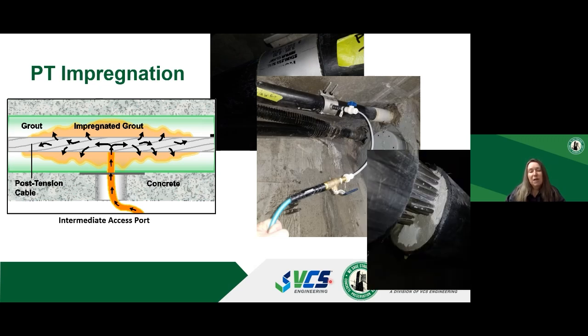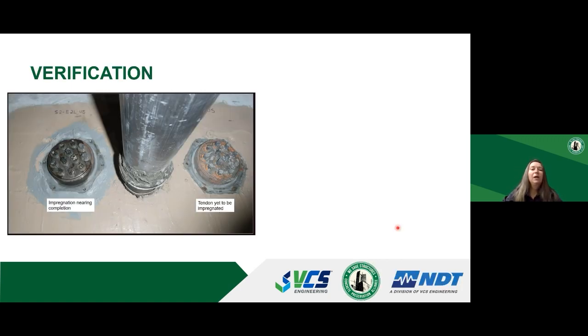Next, after the saddle is removed, the impregnation can be confirmed. Here you see the darker color of the grout. This is the penetration of the impregnation material. And also in impregnated areas, the strands have a higher sheen to them, which confirms the presence of impregnation material. Next, please. Okay. Here is a verification of PTI impregnation.